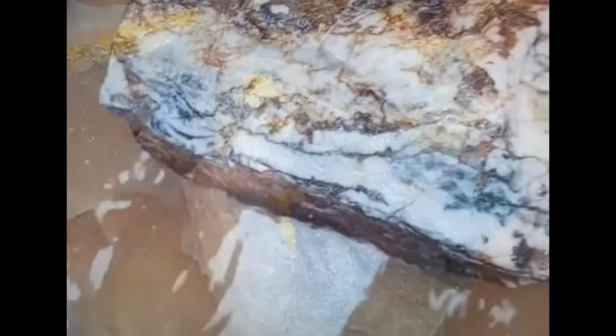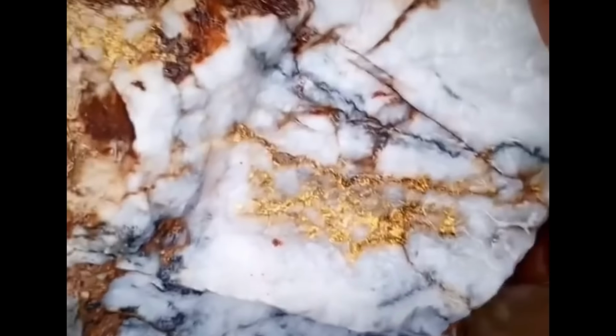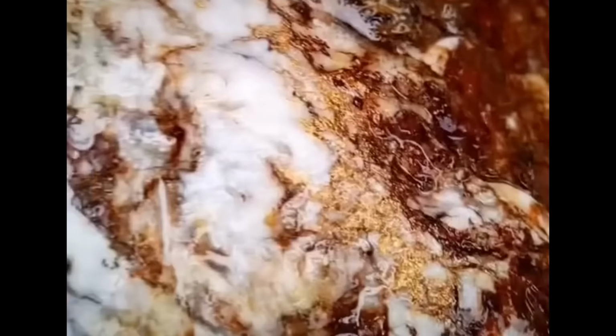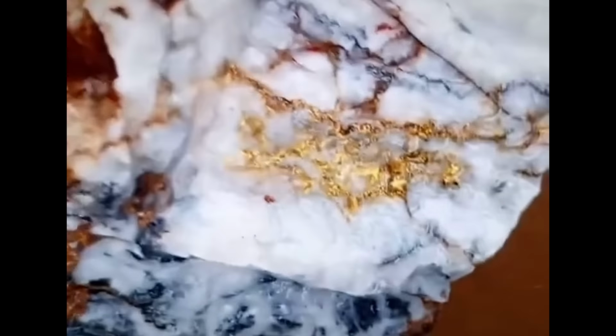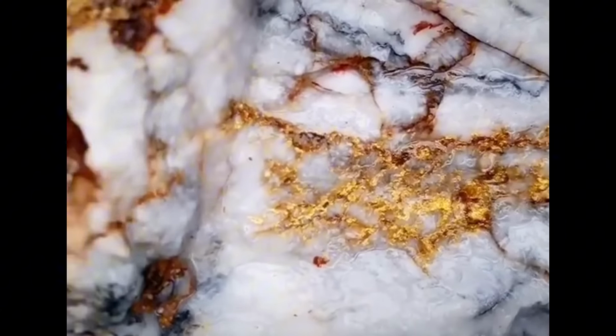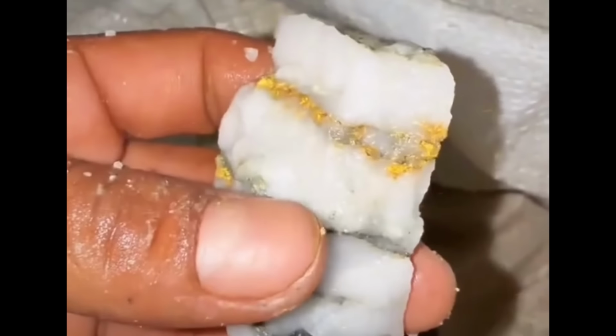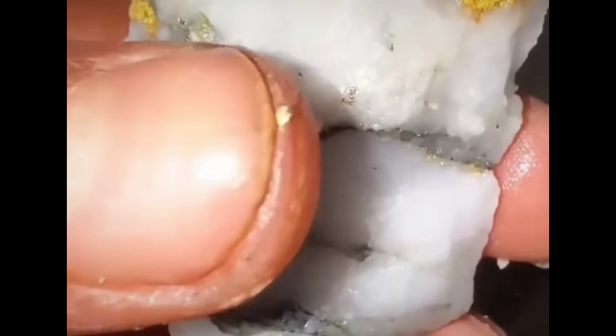No matter how promising a quartz vein looks in the field, gold means nothing unless it can be separated and recovered. That's where crush and pan testing comes in. A low-cost, high-impact method to prove whether gold is actually present. Free milling gold, the kind that's not chemically bound in sulfides, can often be liberated by simply crushing quartz to powder and panning the concentrate. And yet, many overlook this step, relying on guesswork instead of proof.